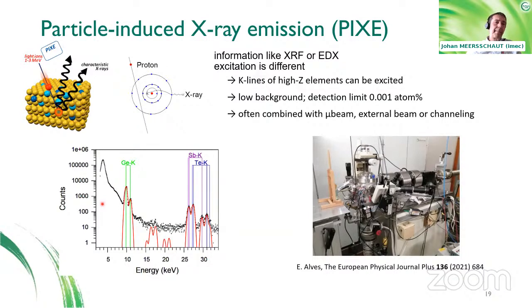And on the other hand, if you have a substrate, you will also have some Bremsstrahlung radiation. The Bremsstrahlung radiation is much less than what you would find with, for example, electron beams. The substrate signal is a property of the principle of the experiment, but it could be overcome by, for example, wavelength dispersive PIXE. This is one of the approaches. I didn't talk about it here, but it's highly investigated in one of the ion beam centers. By using a wavelength dispersive detector, it is possible to selectively measure the low Z elements.